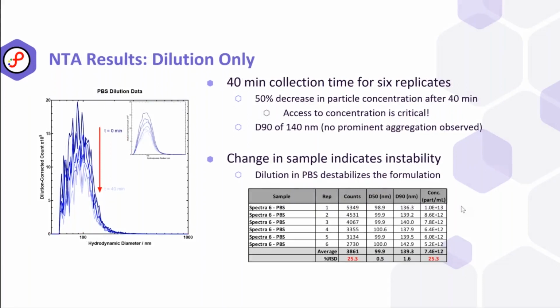If we look at those results over time, so this might be something more along the lines of a stability experiment, or it could even be a formulation development experiment. What we see is that over 40 minutes, we lose 50% of our particle concentration. So literally this last column here in the table shows a monotonic decrease in particle concentration across that 40-minute time frame. Now this isn't something you'd be able to extract from the other types of experiments. And so really access to this concentration information is critical.